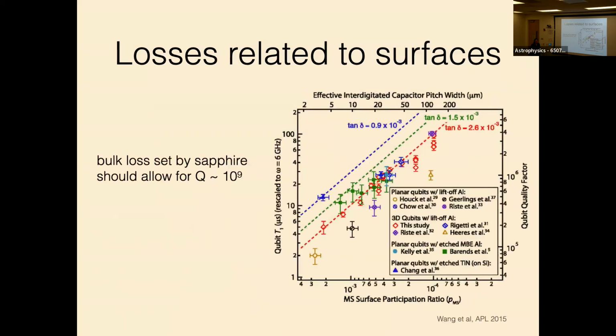So there are a few things that people know about these losses. The first is that the losses appear to be related to surfaces. If you just look at the bulk components, the bound should be something like 10^9 or even 10^10. But people were stuck at around 10^5 to 10^6. And what you can see is that if you make the devices bigger, the quality factors go up. So as you change the amount of participation of your electromagnetic mode with surfaces and interfaces, you change how much loss you see. And there's this very nice parametrization and scaling, from Chen Wang's work several years ago.